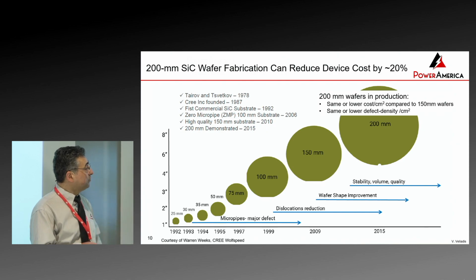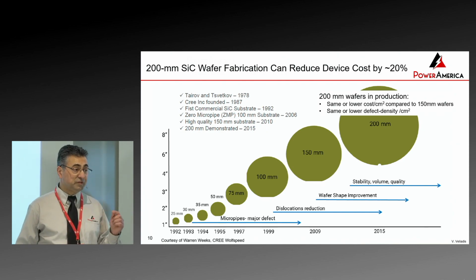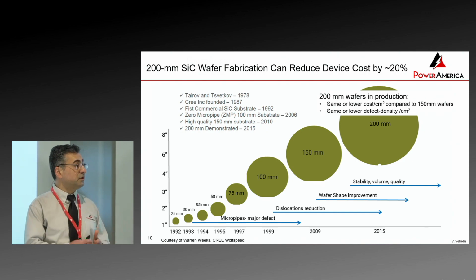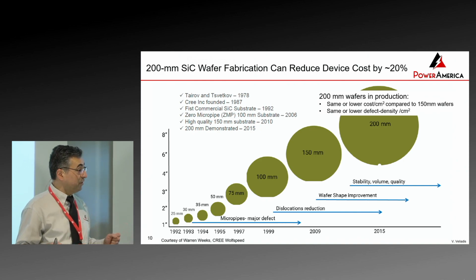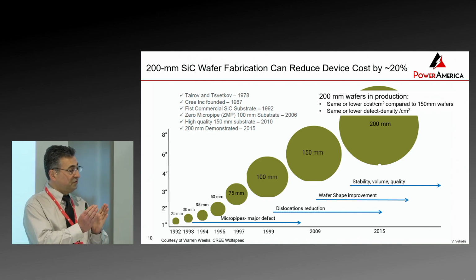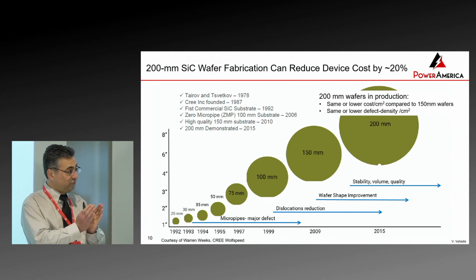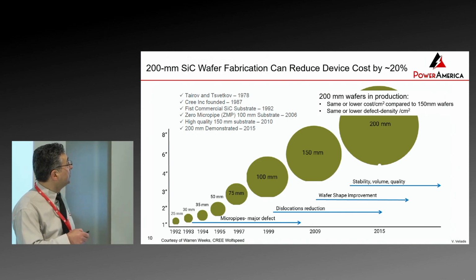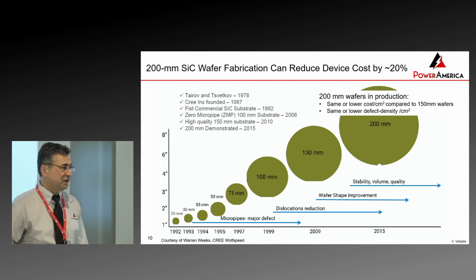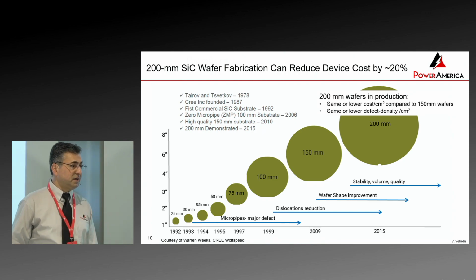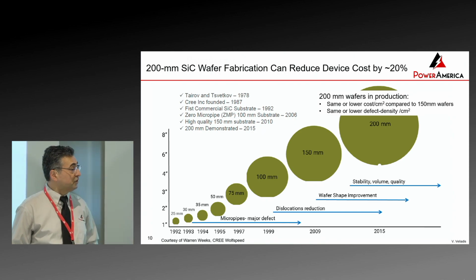If you assume that 200 millimeter wafers will be released with the same cost per centimeter square, because of the higher cost of the wafer, and because you're going to have a 500 micron thick wafer versus 350, so you're going to need a lot more material, I estimate initially about a 20% decrease in cost if you move to 200 millimeter.